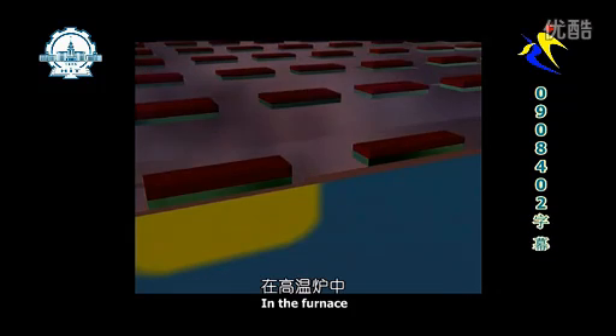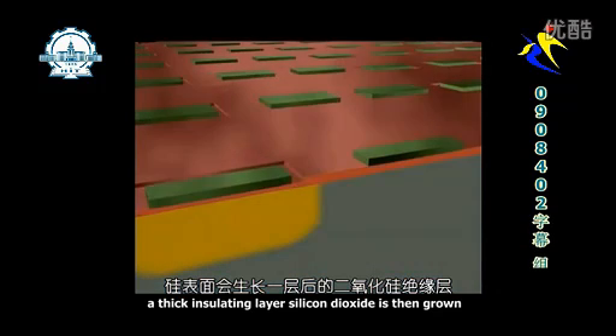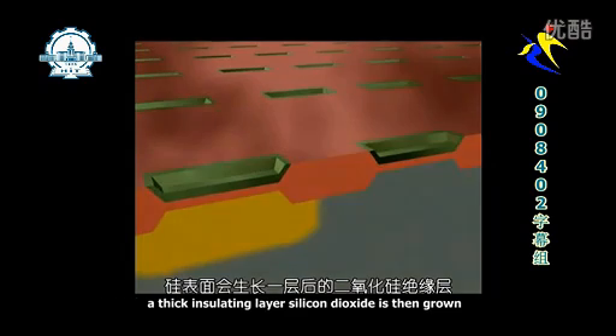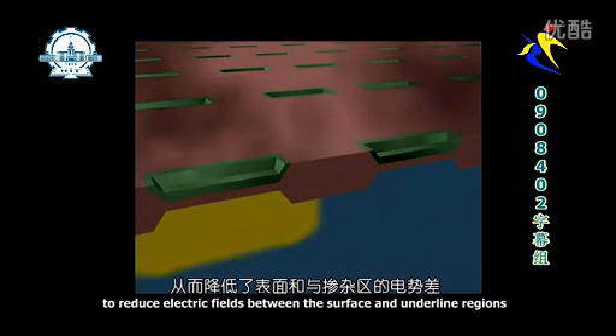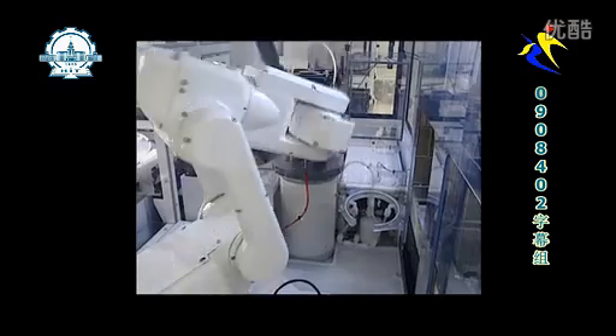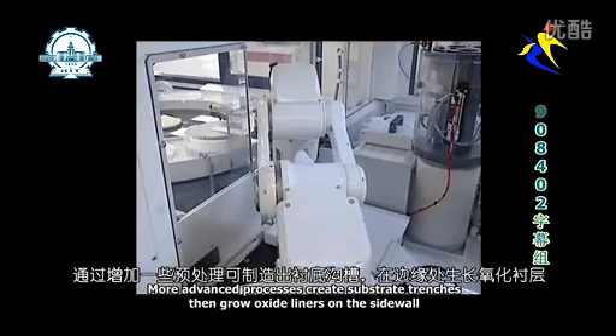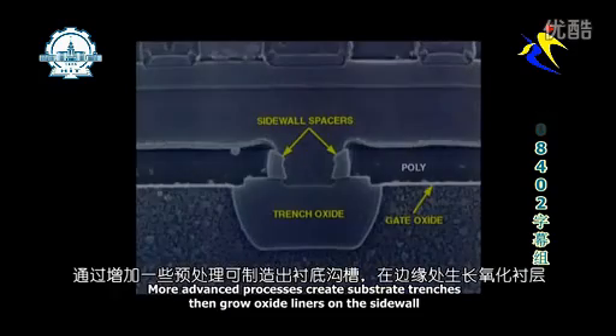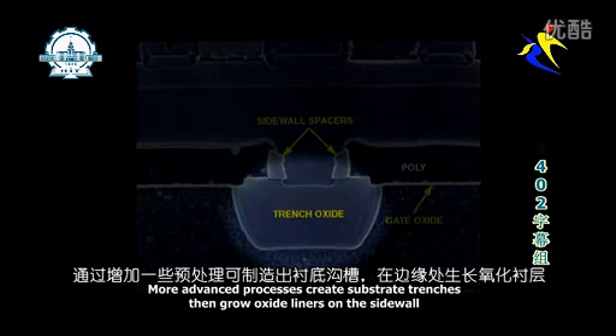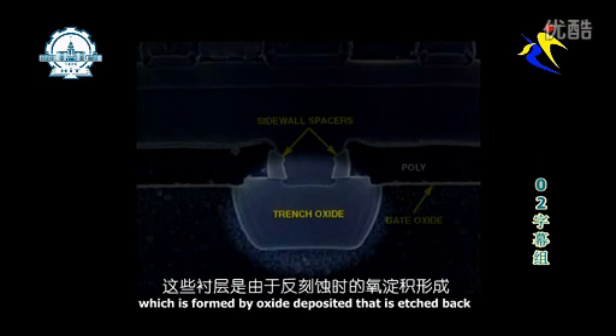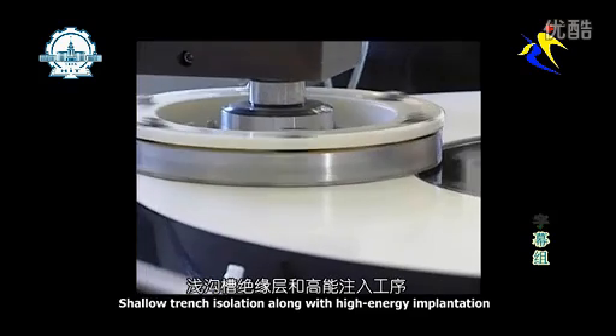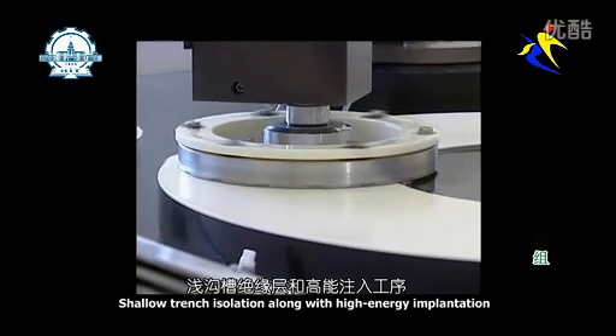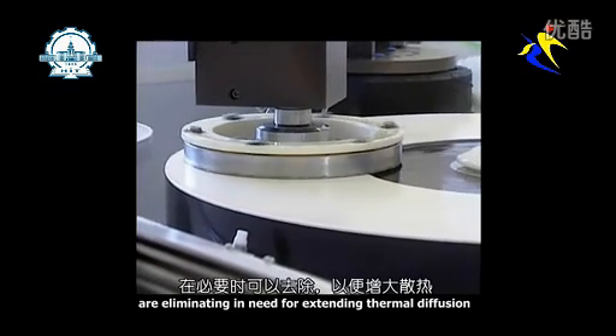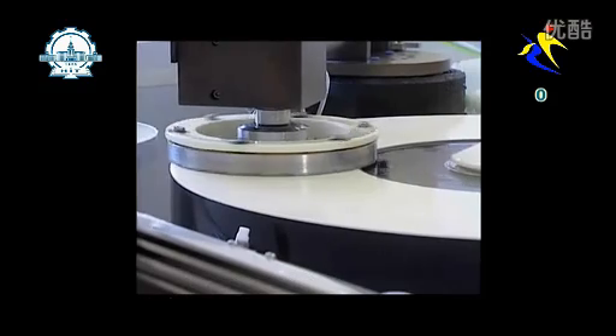In a furnace, a thick insulating layer of silicon dioxide is then grown to reduce the electric fields between the surface and the underlying regions. More advanced processes create substrate trenches, then grow oxide liners on the sidewalls, which is followed by an oxide deposit that is etched back. Shallow trench isolation, along with high-energy implantation, are eliminating the need for extended thermal diffusion.